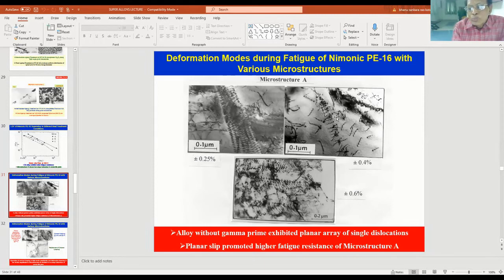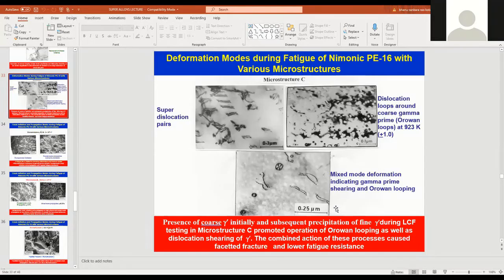But when you peak-age the alloy, these dislocations will not be like this, because your matrix will contain gamma prime precipitates that will be cut by the dislocations passing through. You have the first dislocation cutting the precipitate and the second dislocation passing through. I was talking about the strengthening mechanisms.